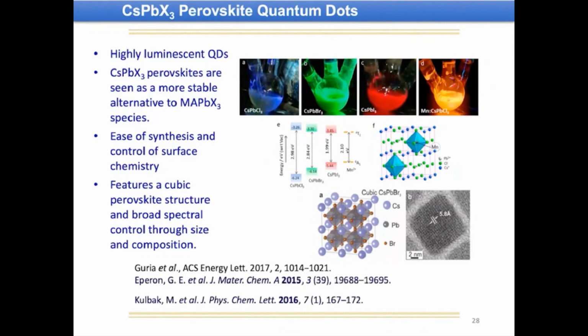Just like you discussed cadmium selenide quantum dots, you can also make cesium lead halide perovskite quantum dots. The picture here shows cesium lead chloride, cesium lead bromide, cesium lead iodide, and the last one is manganese doped cesium lead chloride. These have different band gap energies. As a result, they absorb in different regions of the visible spectrum and also emit light. Many of these materials emit close to unity in terms of emission. So they are bright glowing nanocrystals, and that has created a lot of curiosity about using them for energy harvesting applications. Most of these are cubic structure.